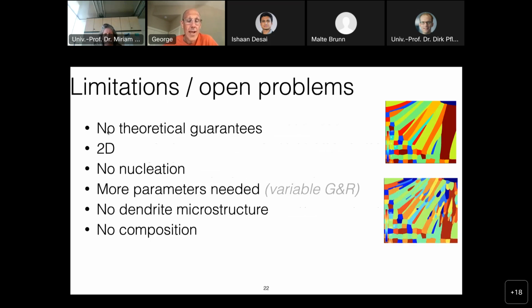One problem that we have, unlike standard PDEs, is there are no theoretical guarantees. It's only 2D. We don't model nucleation. Nucleation is when we have a grain growing here and then another grain starts nucleating. And in certain materials, in certain processes, this is an important phenomenon. In additive manufacturing, not so much because the time scales are so fast, but it's something that we're looking at. We didn't try to model the dendrite microstructure and the alloy composition, which is important, but we have ideas on how this can be done on top of that.